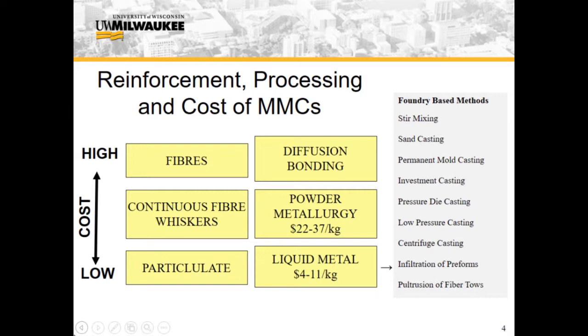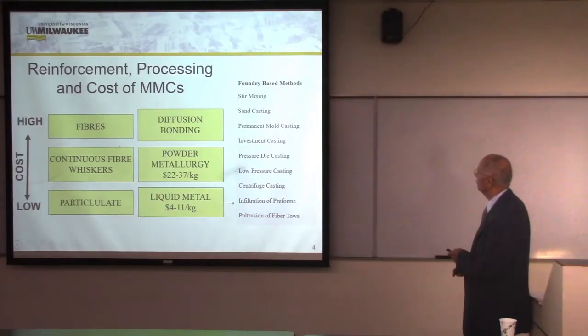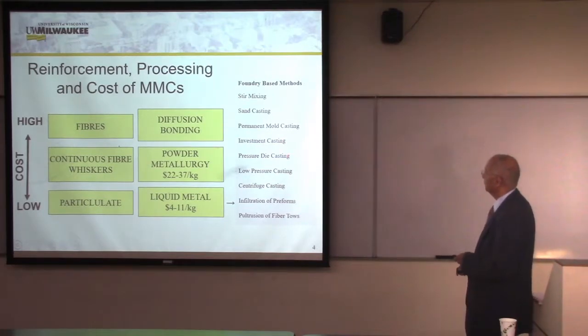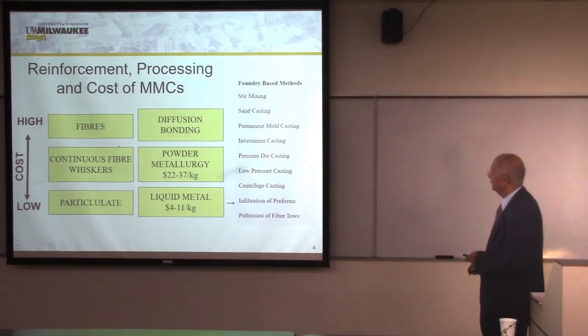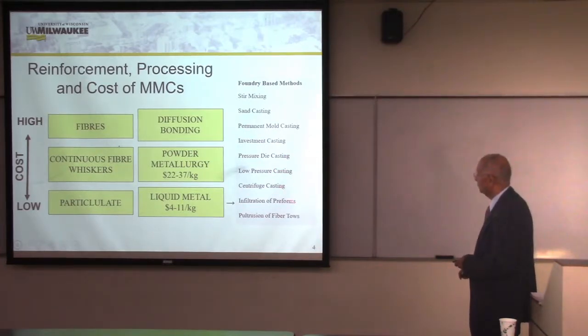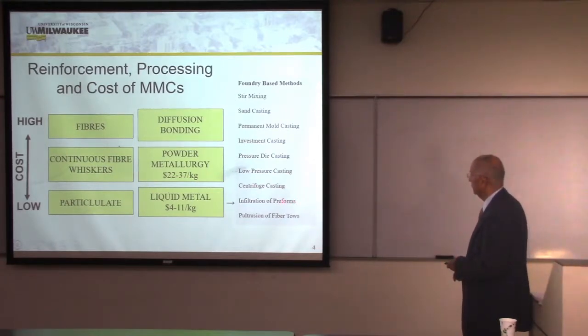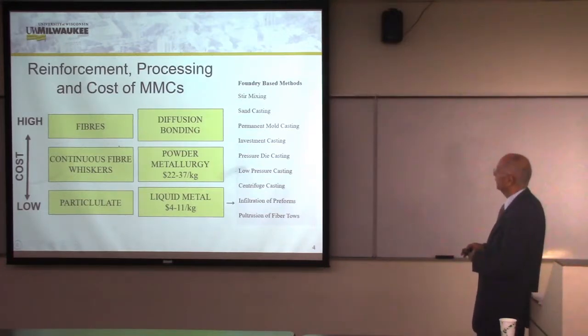Why have I been working with foundry techniques? Because this is the lowest cost method to produce metal matrix composites. The foundry techniques that have been used to produce metal matrix composite castings involve stir mixing, followed by sand castings or permanent mold castings, investment castings. Metal matrix composite castings have been made by high pressure die casting, low pressure die casting, centrifugal casting, infiltration of preforms or loose powder beds by liquid metal, and pultrusion of fiber through the melt that I will show you a little later.